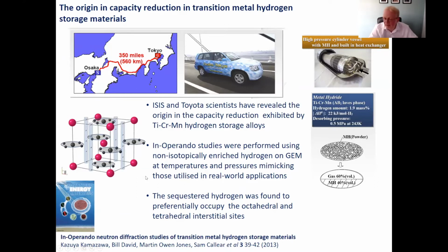We put their alloy in the beam, and what we saw was absolutely nothing. And the reason we saw absolutely nothing was that the combination of titanium, chromium, and manganese alloy that they had for their hydrogen storage material actually had a zero neutron scattering, which meant that when we put the hydrogen in, all we saw was the position of the hydrogen. So we loaded it up with hydrogen, and then we desorbed the hydrogen, and we saw which hydrogen was sequestered within the metal structure. Then we took it across to Diamond, and X-rays couldn't see the hydrogen, of course, but they did allow us to see all the metal atoms.